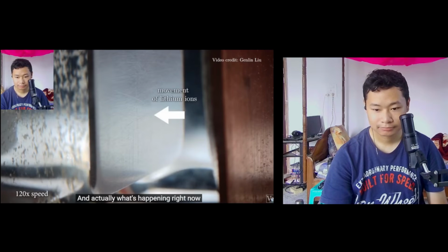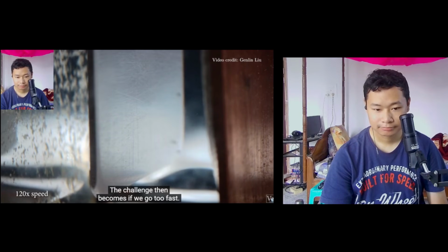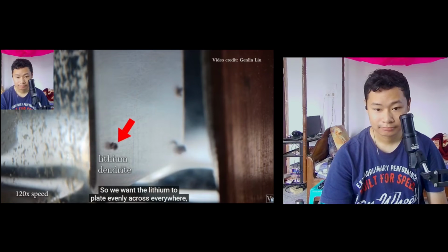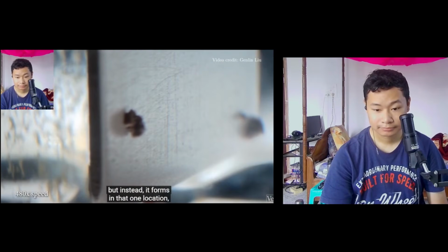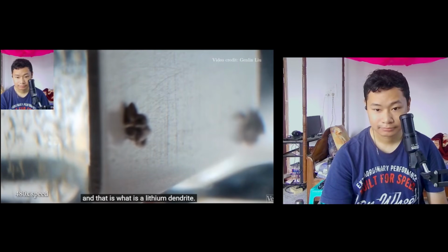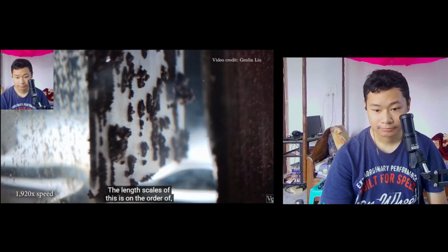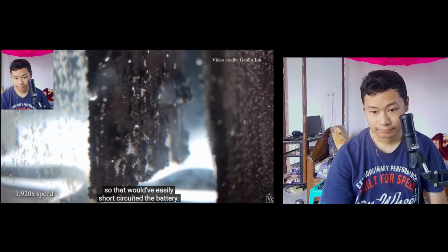And actually what's happening right now is the ideal reaction, where it's very slow. We're getting a dense plate. The challenge then becomes if we go too fast. Oh, that is huge. Everything's fine until all of a sudden it's not fine. So we want the lithium to plate evenly across everywhere, but instead it forms in that one location. And that is what is a lithium dendrite. That lithium dendrite can grow. The length scales of this is on the order of millimeters. So that would have easily short-circuited the battery.